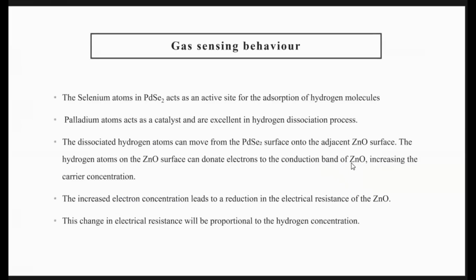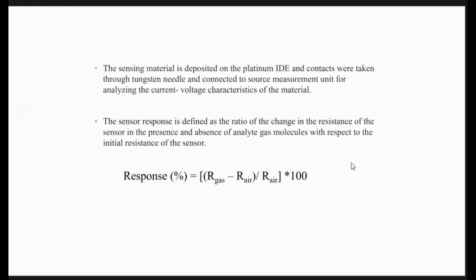So how this sensor works: we had palladium selenide layers. These selenide layers help in the trapping or adsorption of hydrogen gas over their sites. And this palladium acts as a catalyst for breaking these hydrogen molecules into hydrogen atoms. And this hydrogen later gives electrons to the conduction band of the zinc oxide, which increases the conductivity. So by this technique, we got the sensing of hydrogen.